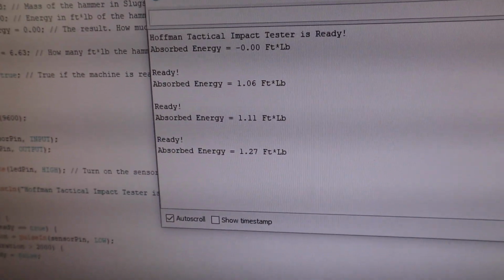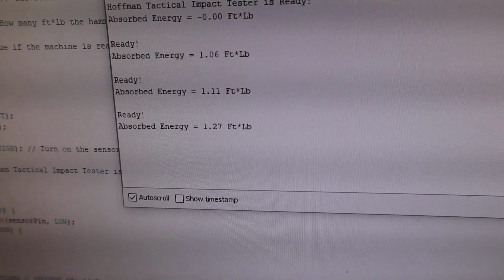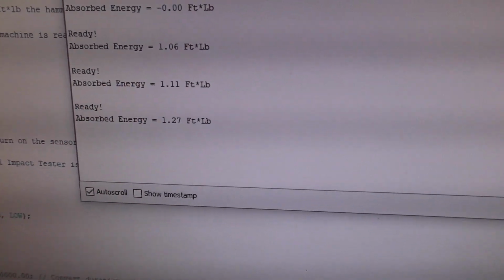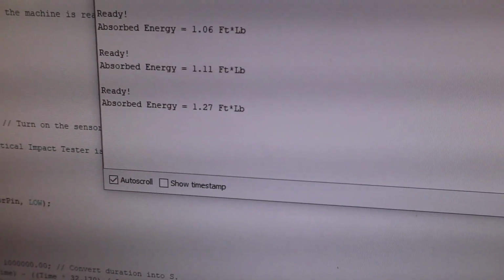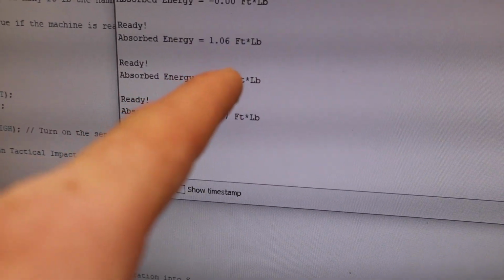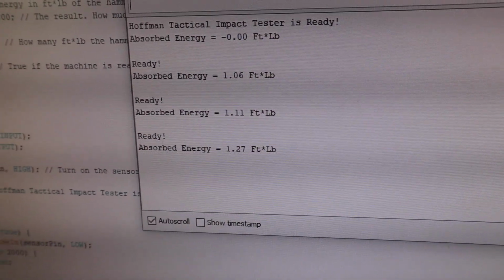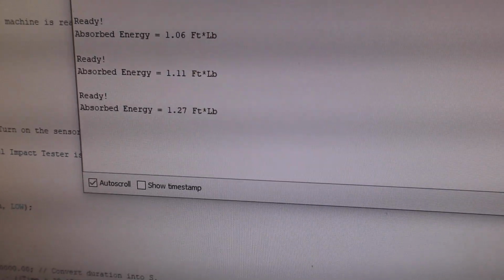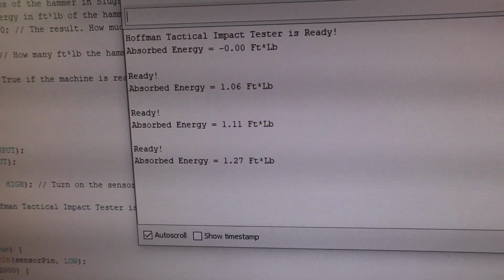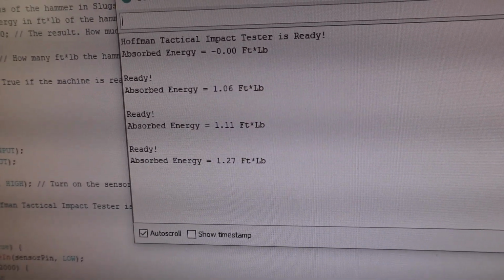Also relatively consistent, not quite as consistent as the horizontal test samples, but we only absorbed about, and yes, I am touching the screen. It doesn't really hurt it. It's good for the video. 1.06 foot-pounds, 1.11, and 1.27 foot-pounds, so like a quarter the impact resistance of the vertical test sample, but still actually not horrible.